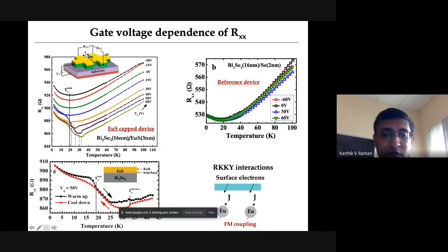Okay. And therefore this is typical around the phase transitions, ferromagnetic phase transitions, where you do expect a hysteresis to open up, primarily driven by these variations in the domain size. Because of this variation in domain size, which also affects the transport measurements, you give rise to such hysteresis loops, especially around the place where Curie temperatures are forming.